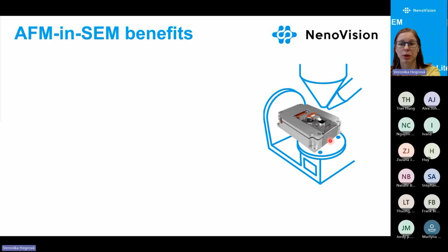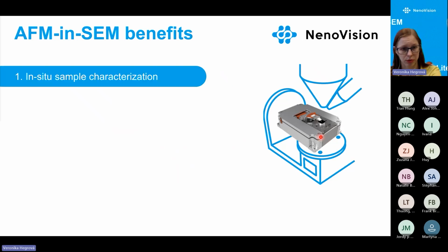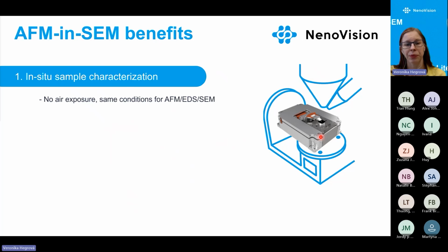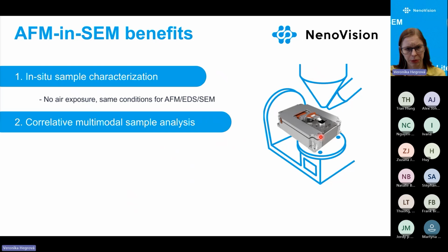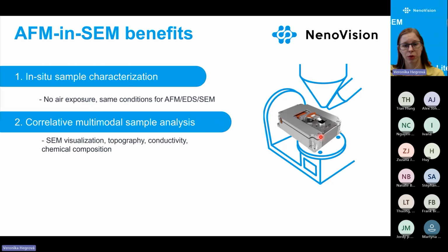And so what are the benefits of such combination? We are able to measure in situ, both SEM and the AFM. So there is no air exposure. We are measuring in the same conditions for AFM, EDS, SEM analysis, conductive AFM, and so on. We can measure correlatively from visualization of SEM through topography, conductivity, chemical composition, or sample prep.